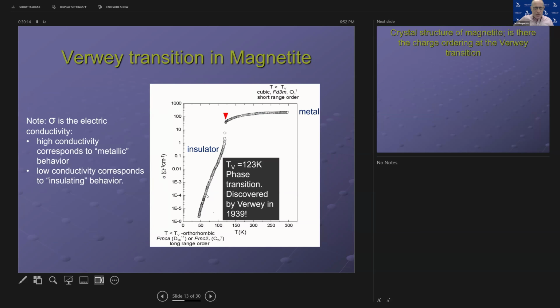I mentioned the Verwey transition in magnetite. What you see here is the graph of conductivity of magnetite as a function of temperature. On the x-axis, you have temperature measured in Kelvin, and just to remind you, 300 K is about room temperature. 0 K is very cold. It's basically negative 273.15 degrees Celsius. The scale on the y-axis is conductivity, which is the opposite of resistivity, which basically tells you whether the material is a good conductor or a bad conductor.